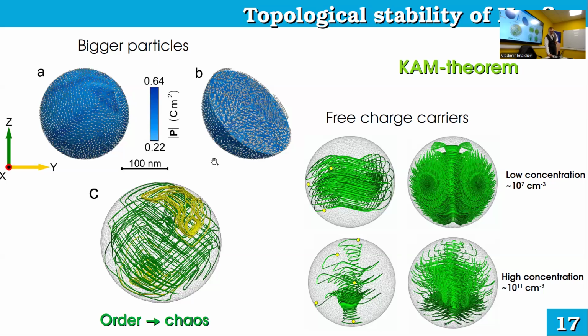Also, we estimated the stability of hopfions, for example, against free charge carriers. So it introduces the electrostatic equation, and you can see that with some low concentration, less than in semiconductors, some lines start to abruptly end on the surface. But still, in the volume you have the presence of tori. And with some high concentrations, something like semiconductors, maybe a little bit higher, of free charge carriers, you get the whole state destroyed. You see all the lines now abruptly end on the surface, and you have no signs of tori inside this nanoparticle now.